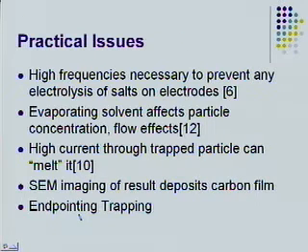So in practical terms, what we found and what other people have found is that you need high frequencies to do this, because otherwise you might get electrolysis from salts in your solution on your electrodes, which is bad because then you create leakage current paths and it destroys your ability to measure the very low current that you get through a couple of molecules. And also, as your solvent evaporates, as we've seen earlier, you create flow and streaming effects at the outside as the size of the little drop that we put down on our electrodes decreases, and you drop colloids out of solution. You create all sorts of weird flow effects, and it affects your actual experiment.